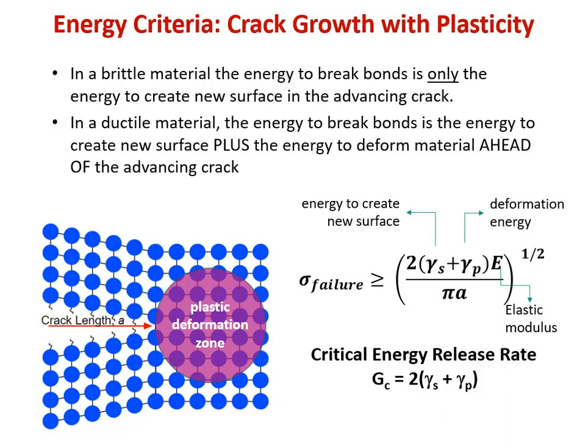So now if we start adding up the energy responsible for breaking bonds and for propagating that crack, and we write it in terms of the stress for failure rather than just the energy to break a bond, we see we've got two main components. We now have the stress at failure needing to be more than our two main modes of absorbing energy for a given crack length. So the components on the right-hand side of our upper equation are 2 times, now we have two energies. One is gamma sub s, a different Greek symbol, the energy to create a new surface, which has a subscript s, and the deformation energy with a subscript p for plasticity.